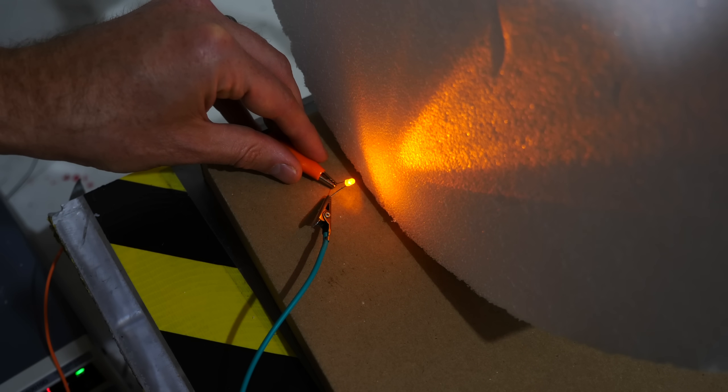And what does all that mean? It means when you heat up an LED light, it changes the light to be more towards the red end of the spectrum as opposed to the blue end. So one way to increase the heat in the LED is just to overdrive the voltage. Just crank up the voltage so more amps will be going through it than should be, and so it'll heat up. And once it heats up, you should see the color change. So let's try it on our orange LED here.